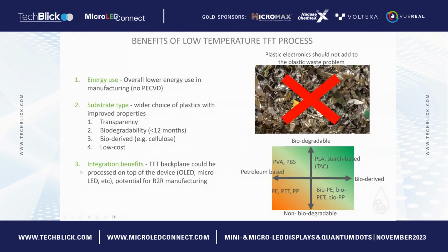And then the last integration is integration benefits, and I will highlight this today in the way in which we make the micro-LED displays. Because of the low temperature, we can process the backplane on top of the LEDs rather than the other way around. And that's because normally micro-LEDs would be damaged if you took it up to, say, 360 degrees C for the PECVD process.